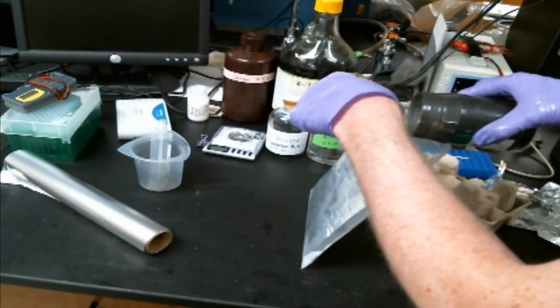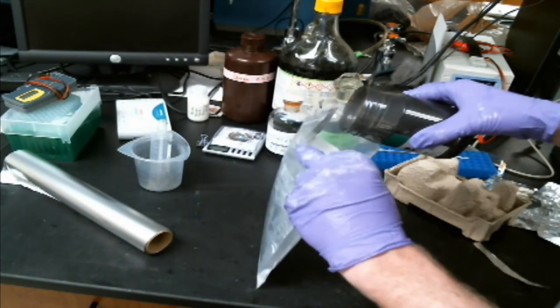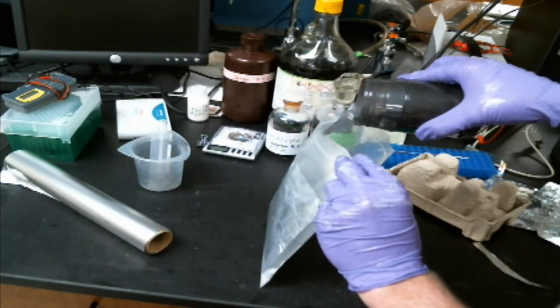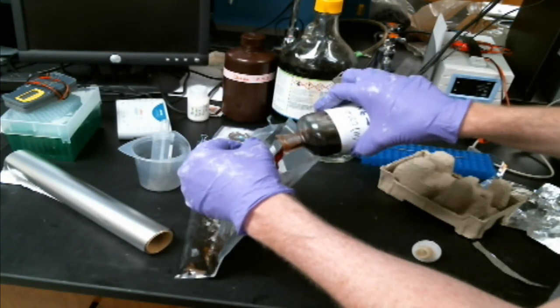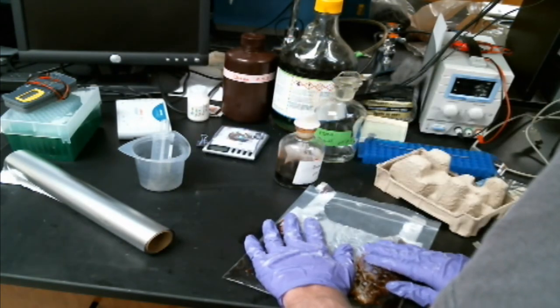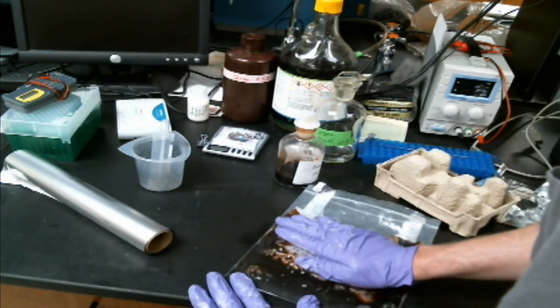Once I've got my iron anode, I'm going to sprinkle some graphite powder into the cathode layer to try to keep everything separate, and then I add the iron EDTA to the cathode layer. That's going to absorb the electrons that are generated when the iron is oxidized.